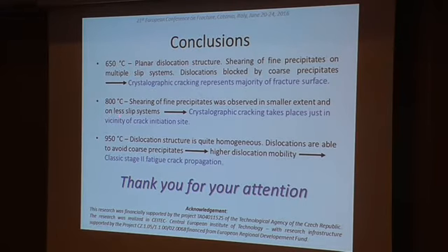At 800 centigrades, shearing of fine precipitates was also observed, but to a smaller extent and on fewer slip systems. Therefore, crystallographic cracking took place just in the vicinity of crack initiation sites, and further crack propagation was in stage 2 mode.